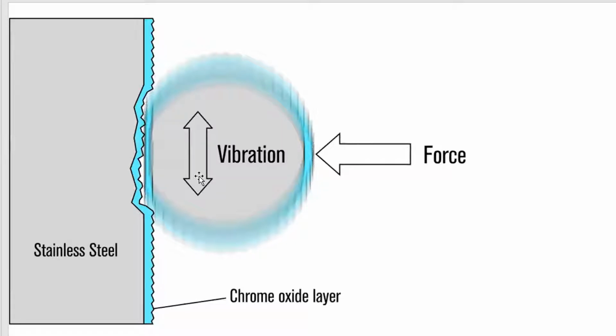It's probably not stopped. It's kind of a continuous process of wear and reestablishment of the oxide layer. And then once that oxide layer is reestablished, you have two very hard surfaces in contact, which also have some little crunched up pieces of chrome oxide. And so that's how that wear accelerates. So it's constantly going on. It can go on until this part is actually locked into this part. You can see this is starting to key in to this.